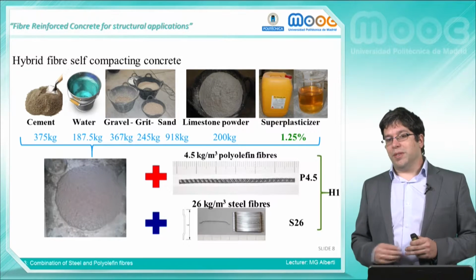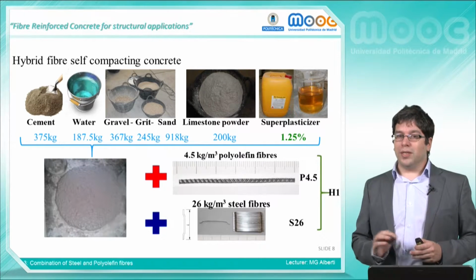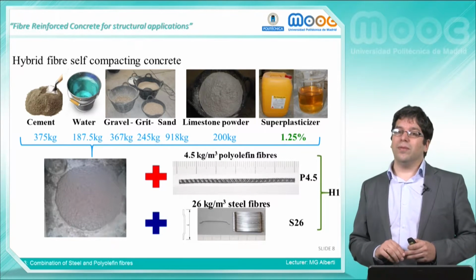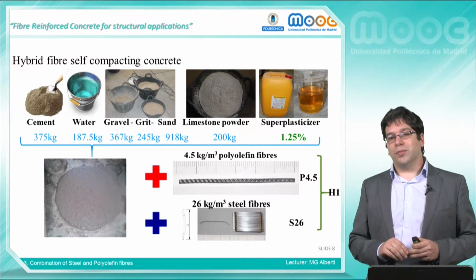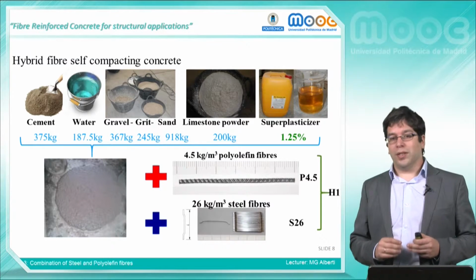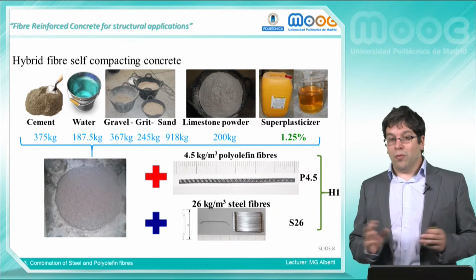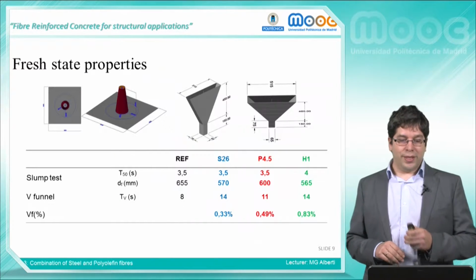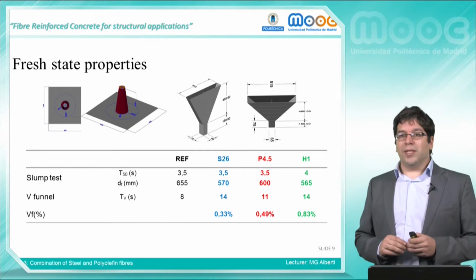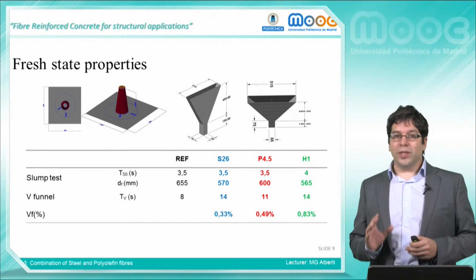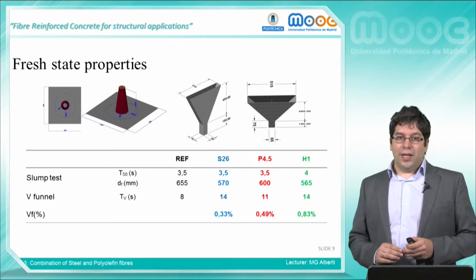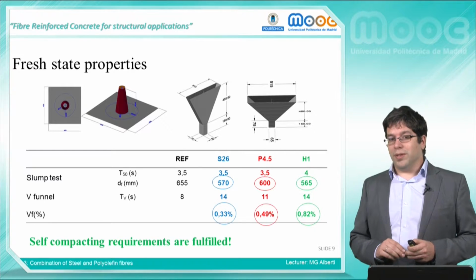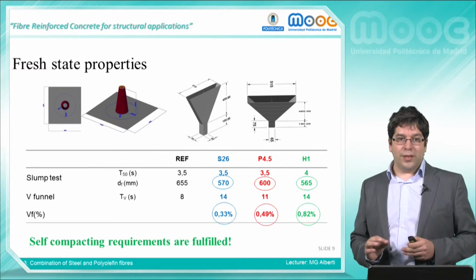4.5 kg/m³ of polyolefin fibers and 26 kg/m³ of steel fibers were chosen in order to maintain the volume fraction at about 0.8% when both types of fibers were mixed. The fresh properties were maintained, and the higher influence of the steel fibers was visible. Even with the total amount of fibers, self-compacting properties were reached.